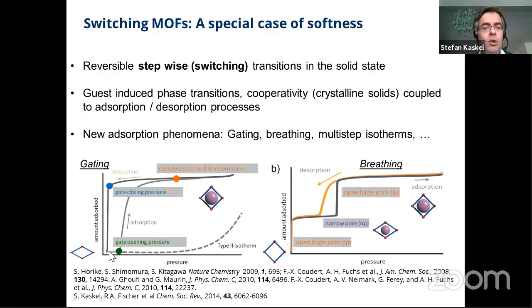So one step switching, and this is what we call gate opening or gating behavior in this type of framework. The other also quite frequently observed phenomenon is the breathing. Here, the open pore form is more stable without any guest. Here it is different: the closed pore form is more stable when the guest is absent.